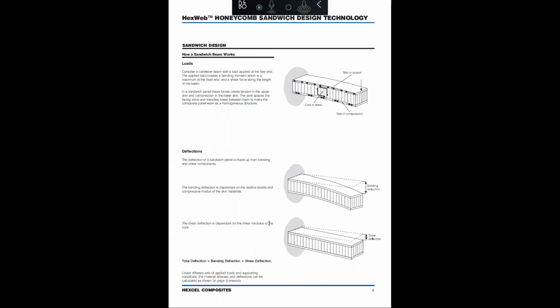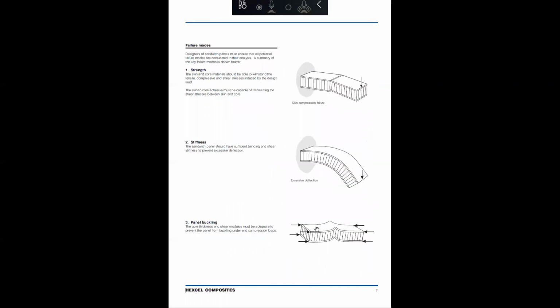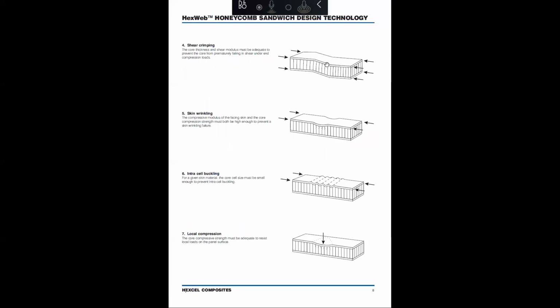It will also talk about loads, deflections, the failure modes you can have: skin compression failure, so the skin fails, excessive deflections due to perhaps the core has lost its stiffness, panel buckling, shear crimping, skin wrinkling, intracell buckling. And for shear crimping, the core thickness and the shear modulus has to be adequate to prevent the core from prematurely failing in shear.